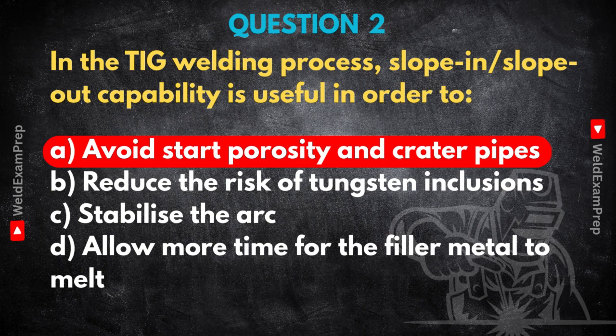This lets the molten pool cool and solidify slowly, completely. If you just cut the power suddenly, the center cools last and shrinks inward, often leaving a hole or a dip. That's your crater pipe. And it's not just ugly, it's a weak spot, a stress riser, a place where cracks love to start. So controlling those starts and stops is crucial for the integrity of the whole weld.